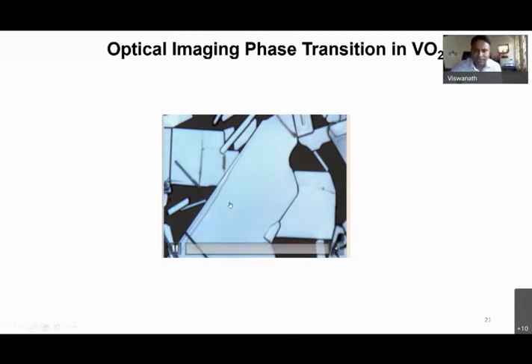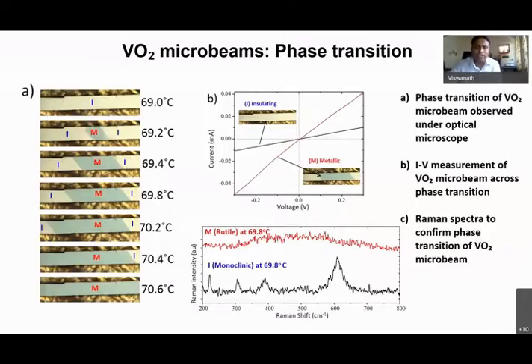So the idea is, we know clearly, in relatively large crystals, where the phase transformation is actually happening. So it is possible to selectively do indentation. That is exactly what we have done. For example, at 69 degrees Celsius, the entire crystal is in the insulating state. But within 0.2, 0.4 degrees Celsius, we can see a nucleation of a metallic domain. And slowly the metallic domain is expanding and consuming the insulating state.